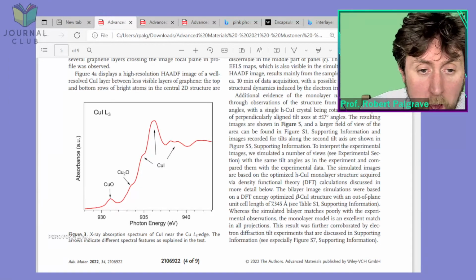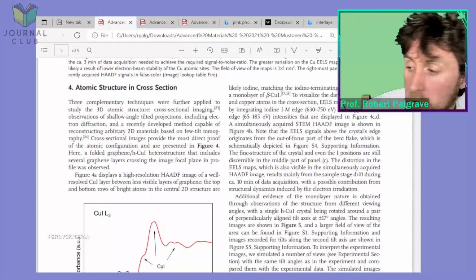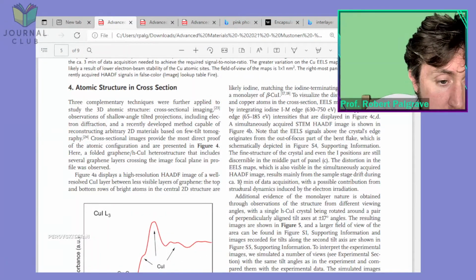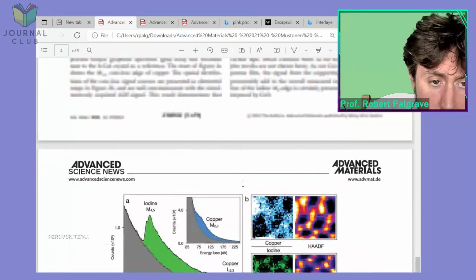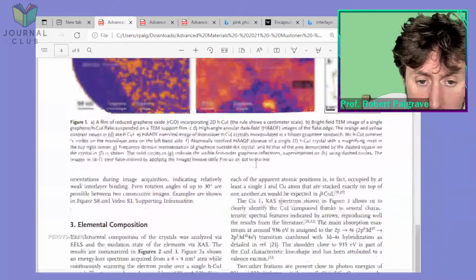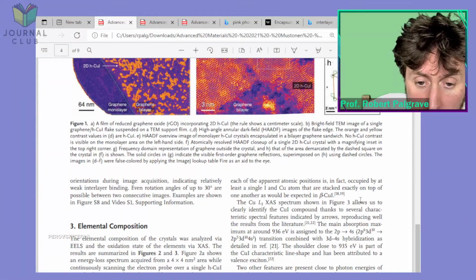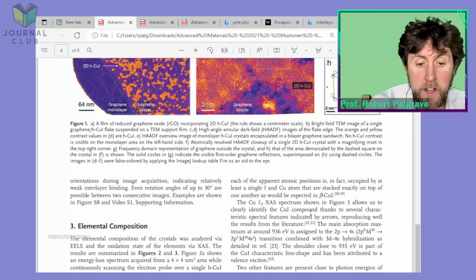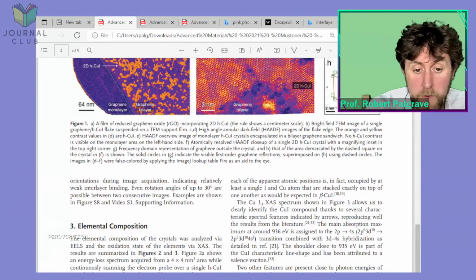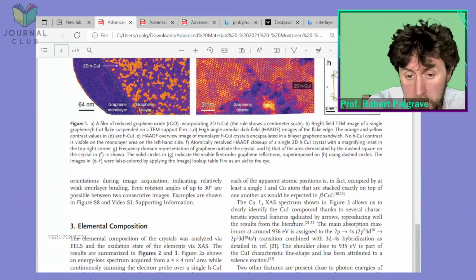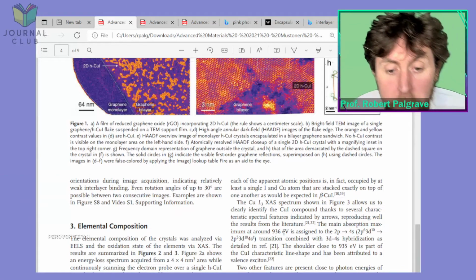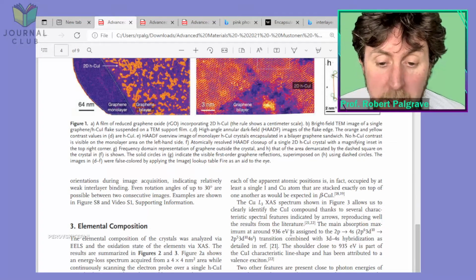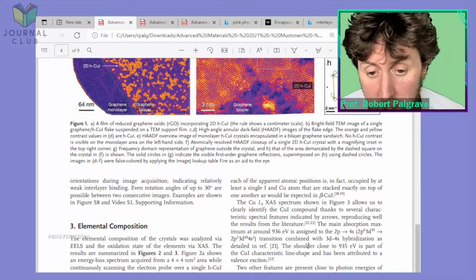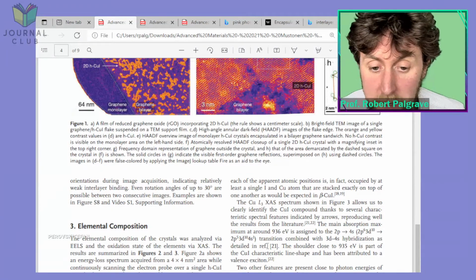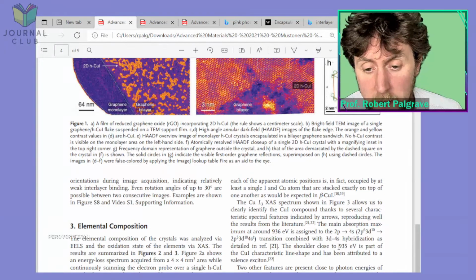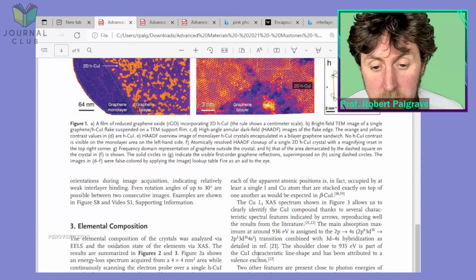I would definitely want to go and look up the interpretation of these. I think they've done an okay job talking about this, oh, it's further up actually where they talk about the XAS, sorry. So let's just see what they say. The copper L3 XAS spectrum shown in figure 3 allows us to clearly identify the cuprous iodide compound thanks to several characteristic spectral features indicated by arrows, reproducing well the results from the literature. Okay, so we could go and look at these if we were interested. The main absorption maximum around 936 electron volts is assigned to 2p to 4s transition combined with 3d to 4s hybridization as detailed in reference 21. The shoulder close to 935 eV is part of the CuI characteristic line shape and has been attributed to